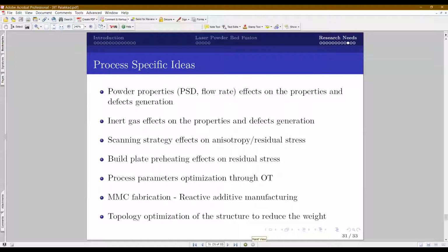Scanning strategy effects is one of the important things to minimize the residual stress and anisotropy, that is the grain formation orientation. So there are a lot of things that can be explored in this scanning strategy area. Similarly, how to minimize the residual stresses through preheating the powder or the base build plate. Those effects can be studied. And process parameter optimization, which is a very simple and important problem for the new additive manufactured grades.